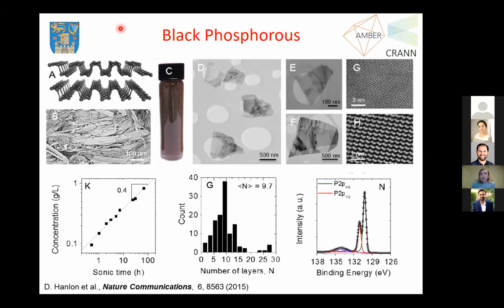Black phosphorus was one of the materials that we managed to exfoliate by liquid phase. This is a very intriguing 2D material, very interesting. Nevertheless, the interest in this material has been dampened a bit, especially due to the instability. The fact that it's very unstable in air, and it degrades, it oxidizes quite quickly.